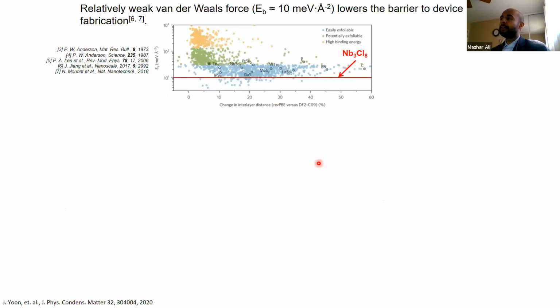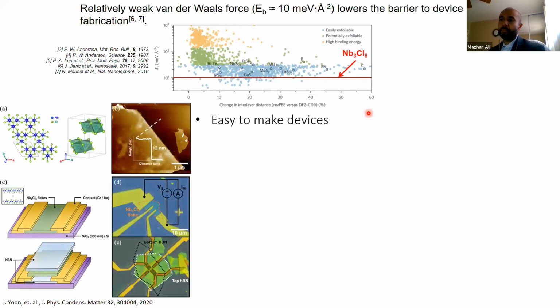So we did that. And like I said, it's very exfoliatable. You can see its interlayer exfoliation energy is less than maybe graphene. So it's really a nice material. And it's also quite stable in terms of atmospheric degradation. So it's a good starting point.